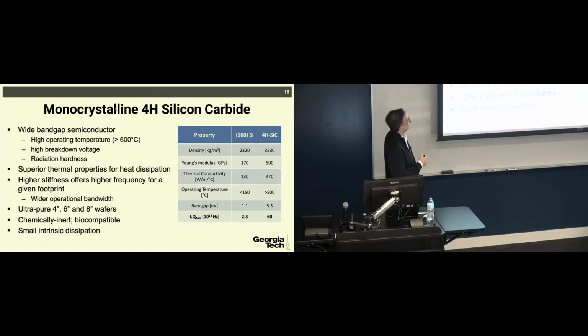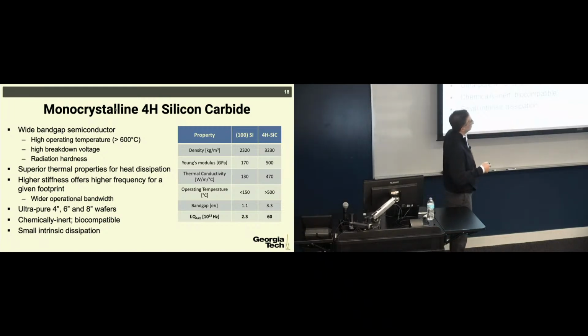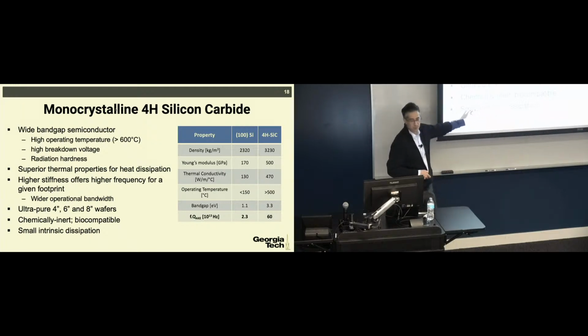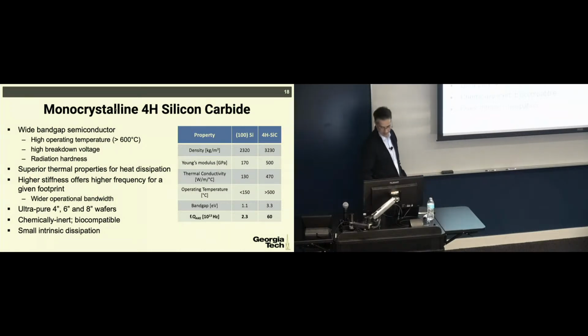In addition to that, it has superior thermal and acoustic properties. You see that the Young's modulus is almost 3 times higher than silicon. The thermal conductivity is higher, and it can withstand a higher temperature. And now I mentioned this F times Q product, and you see that silicon carbide is about 30 times higher than silicon. That is a measure of the intrinsic dissipation because of phonon-phonon interactions in the material. So silicon carbide also has a very small intrinsic dissipation compared to silicon.